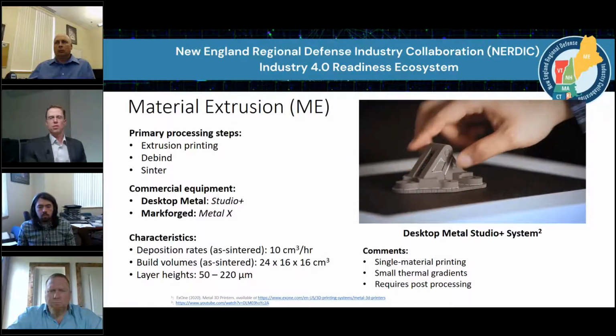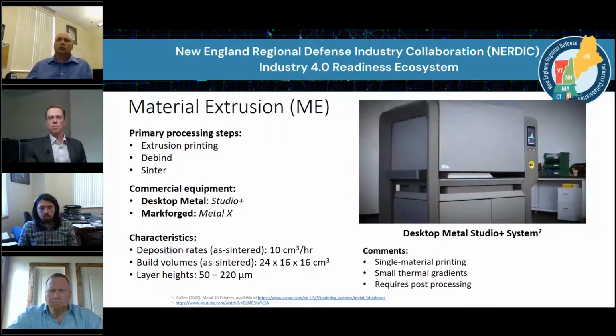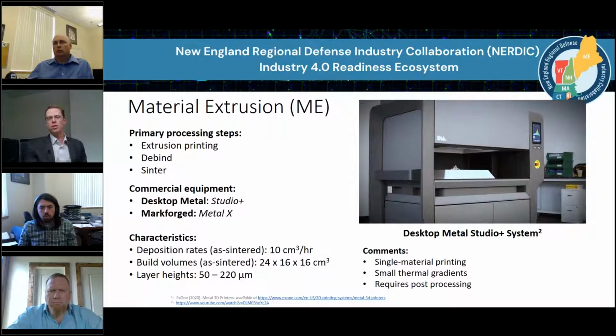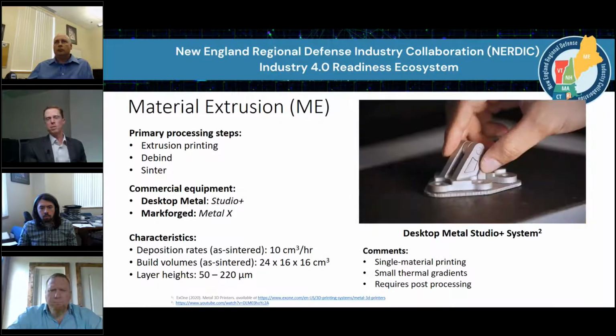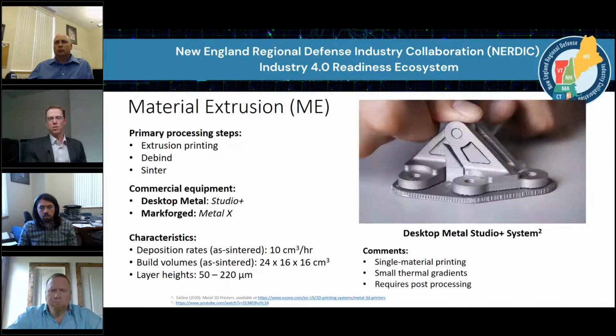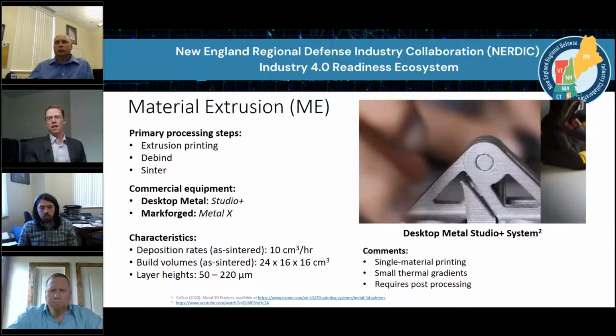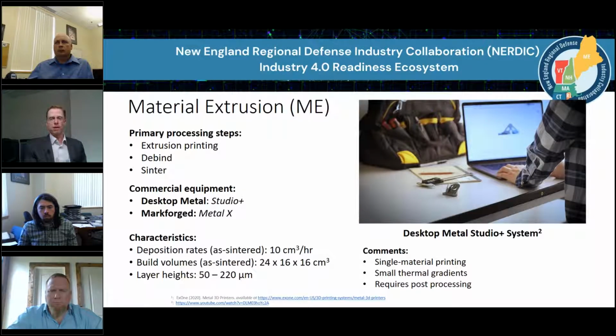And then it goes into a sintering process, and the sintering process elevates temperature somewhere around, well, it depends upon the material, but probably somewhere around 1350, 1400 degrees C. And we have solid metal parts that come out. So essentially, it's a three-step process consisting of extrusion, debinding, and sintering.